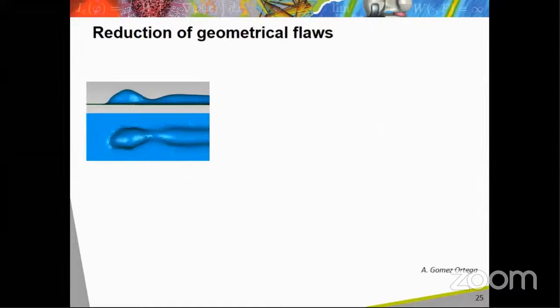I will now present another issue that has required an optimization of the process parameters. It concerns the reduction of geometrical flaws frequently observed at the beginning of the deposit, mainly in aluminum alloys. One can see on this picture, corresponding to a scan of a real deposit, an irregular shape of the beginning of the deposited bed. This kind of defect is frequently observed and can be attributed to a pressure variation in the liquid according to the curvature of the liquid-gas interface.